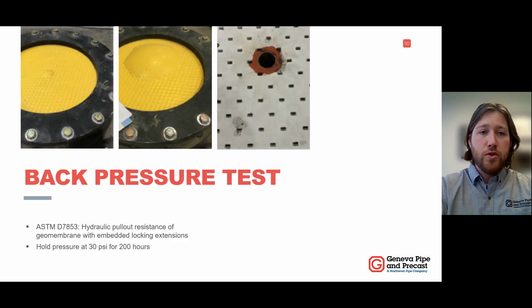Beyond that, we wanted to make sure that not just the coupler, but also the liner itself. So for some reason, if any water pressure was able to get behind that liner, how would those anchors hold up to it? Well, I don't remember if Elena specifically mentioned it, but each one of those anchors holds, I believe, over 100 pounds of pull-out force per anchor, with over 100 of these little anchors per square foot. So right there, we had 30 PSI for 200 hours to see how those anchors would perform, and it was able to hold.